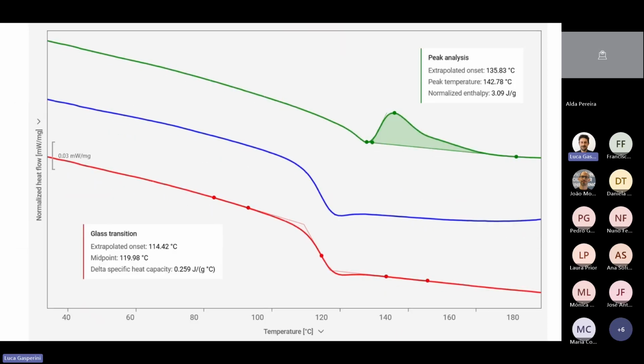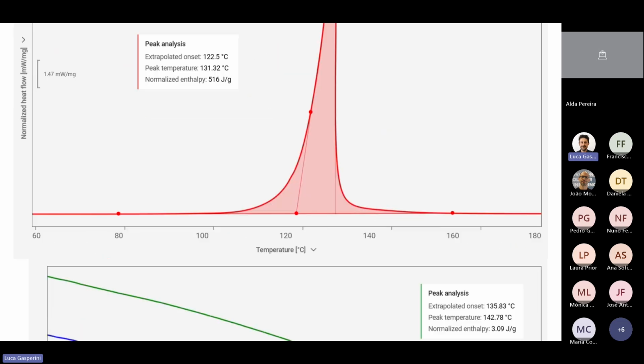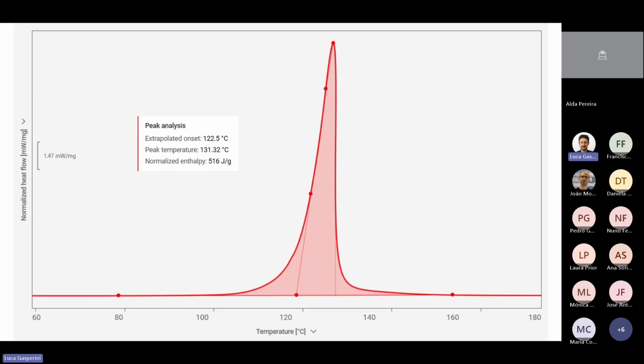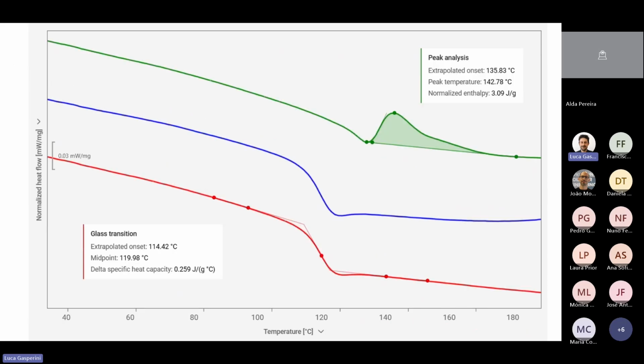But what we also did is we took the material and we looked at the recipe that the manufacturer of this resin is telling us. And the recipe said that to achieve a curing which is sufficient, we can also do this isothermally at a much lower temperature. You see here we heat it to about 180, 190 degrees. But the manufacturer says it's enough if you heat to only 150 degrees and stay there for an hour. You can perform an isothermal curing. So we did, and then we compared.